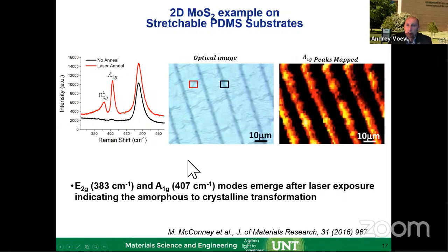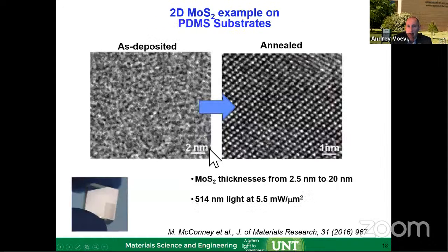And of course, annealing only occurs where you deposit the light. Therefore, as you draw those lines, the material is crystalline only within these lines, and between them it is amorphous, it's insulating. So essentially, you can grow the semiconducting channels with this insulator. It's showing that laser mapping technique producing these channels on molybdenum disulfide.